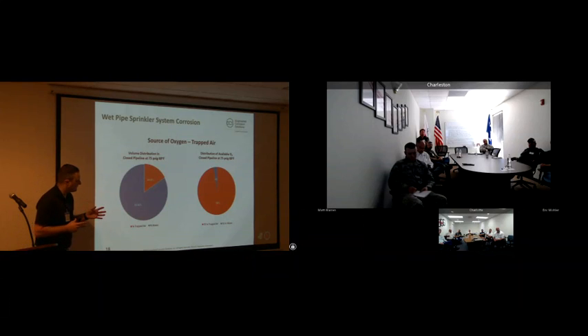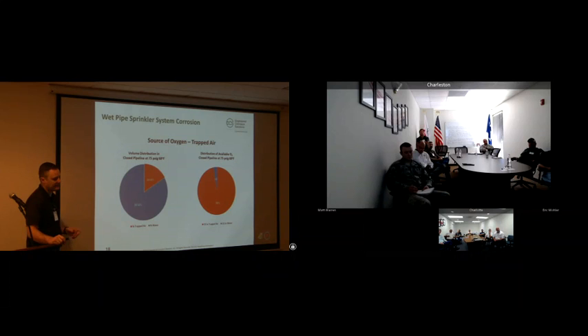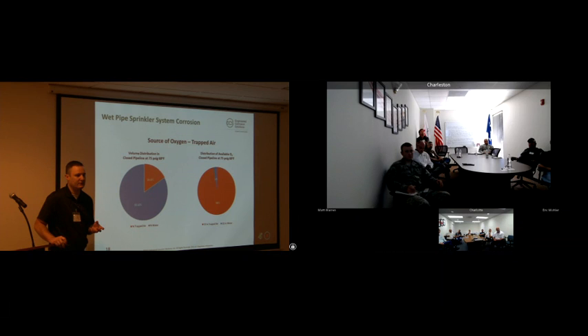And the big red section, which is 99%, that's the oxygen that's contained in the trapped air. That little sliver that's 1%, it's actually a little less than 1%, but the pie slice becomes so small you can't see it. That's what's coming in with the water and the dissolved oxygen content. To address the dissolved oxygen in the incoming source water, you don't get a return on your investment. It's not making a significant difference in corrosion control.